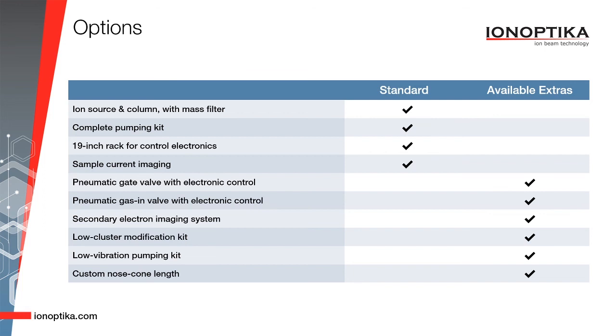One of the difficulties around gas cluster ion beams is the production of large clusters based on different source parameters. And it's actually quite difficult to obtain low clusters. So if low clusters are of interest to you, we can provide a low cluster modification kit. And this allows tuning of the cluster source between argon 1 and argon 1000. For sensitive applications such as SEM and TEM, where vibration is an issue, we can provide a low vibration pumping kit. Where instruments are of non-standard design, we can customize the length of the nose cone such that the working distance is appropriate for your instrument. So we provide a wide range of customization with the GCIB 10S.